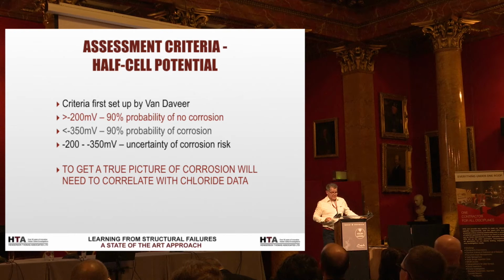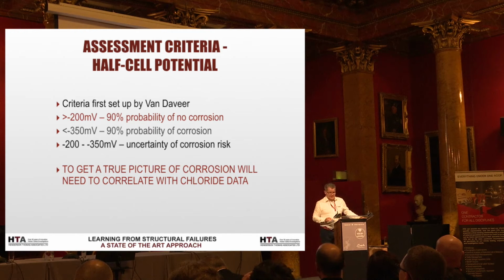You're really using it more as a moisture meter than a corrosion probe. And therefore, because it's completely immersed in water and the concrete is saturated, you tend to find there's no oxygen. If you don't have any oxygen at the site of the bar, generally, you don't get corrosion. So it's just one of the issues that we do have to think about as structural engineers.